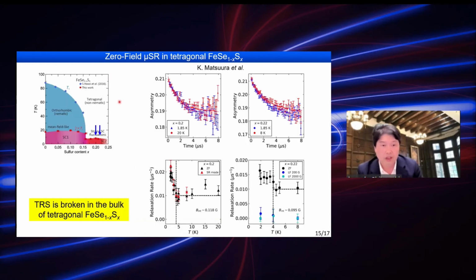We can repeat this kind of measurement in the tetragonal side of iron selenium sulfur, and here is the data for x equals 0.2 and 0.22. We see essentially the similar effect, meaning the temperature dependence of the μSR relaxation rate shows an increase starting from Tc, which is 4 Kelvin in this case.